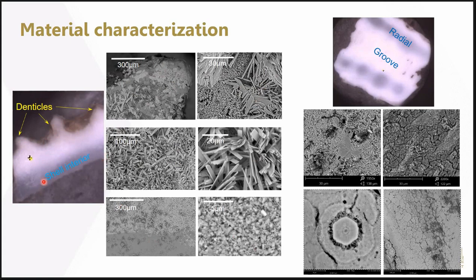part of the shell. Certainly, if the crystal size is very small, we can see a very polished, very smooth surface. And if the crystal sizes are larger, we can see a relatively rough surface. We can also polish or remove the material perpendicular to the shell, parallel to the shell, or perpendicular to the denticle, and look at the crystal morphologies and so on.